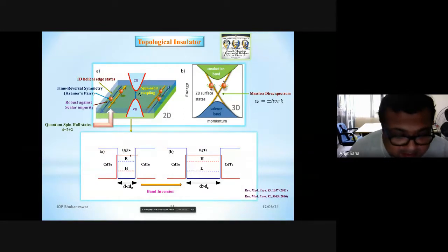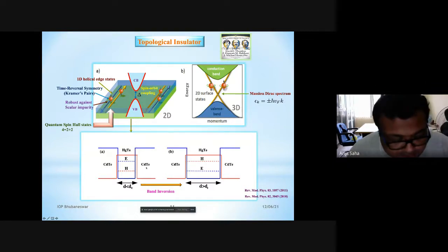So first in the theory, what people have done in this system is, if you think in this picture, you make a quantum well of this mercury telluride, which is sandwiched between two cadmium telluride layers. So this cadmium telluride has been used to make this quantum well structure for the mercury telluride, and in this mercury telluride you have a very strong spin orbit coupling. And if you think about these two bands, let's say an electron and a hole band, they are separated by this gap here, and the width of this well is, let's say, some width d. And now suppose you start changing the width of this well, you change and change.